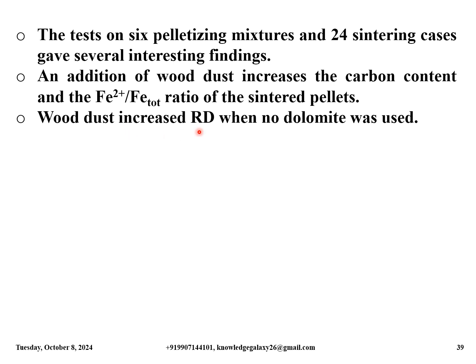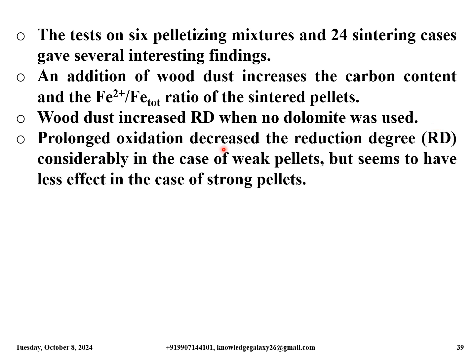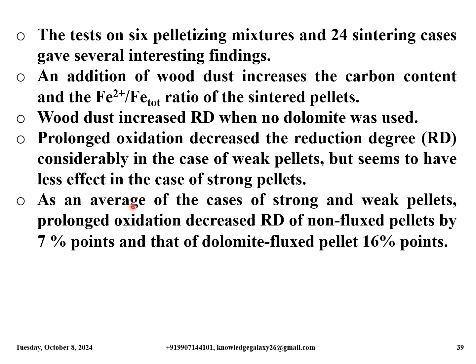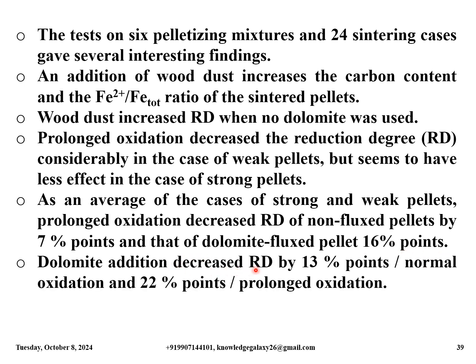Wood dust increased RD, that is reduction degree, when no dolomite was used. Prolonged oxidation decreased the reduction degree RD considerably in the case of weak pellets, but seems to have less effect in the case of strong pellets. As an average of the cases of strong and weak pellets, prolonged oxidation decreased the reduction degree of non-fluxed pellets by 7% points and that of dolomite fluxed pellets by 16% points. Dolomite addition decreased the reduction degree by 13% points in normal oxidation and 22% points in prolonged oxidation.